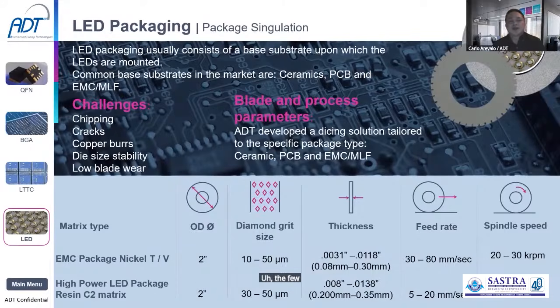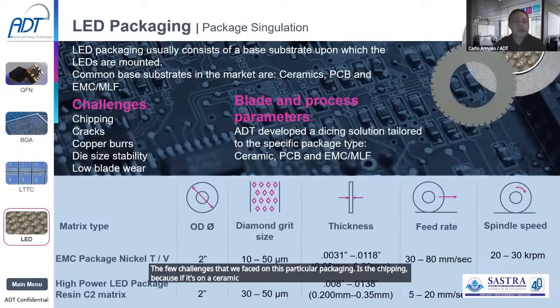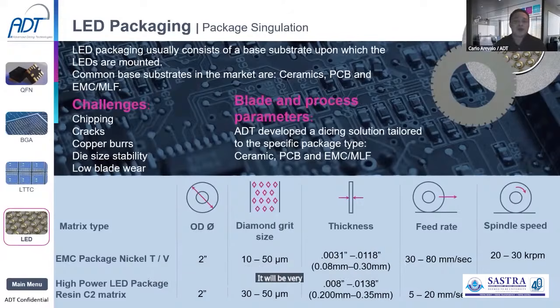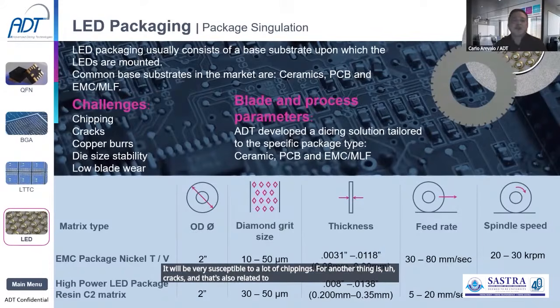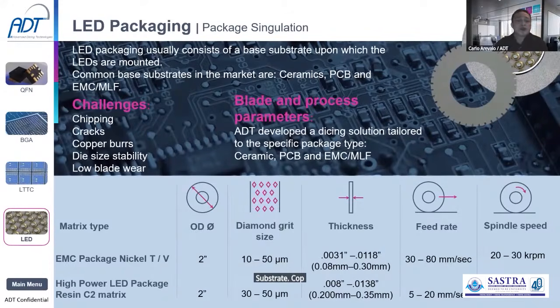The few challenges that we face on this particular packaging are chipping, because if it's on a ceramic substrate, it will be very susceptible to a lot of chipping. Another is cracks, which is also related to a harder type of substrate. Copper burrs, and die size stability, which is related to how the blade is wearing. If you are losing your thickness, the die size will definitely change. And low blade wear. The customers or the market always expect that you deliver a very good amount of blade wear and are able to maintain a significant cost saving.